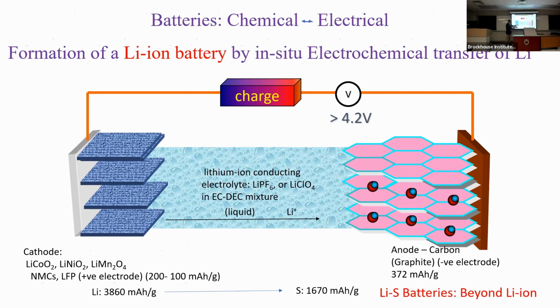But instead of graphite, one way is to use lithium metal, whose capacity is 3,860. I mean, that's the beauty of lithium. It's got so much energy, but by putting it in this structure, mainly for safety, we go down to 372. Yeah, less than 10% of the capacity.